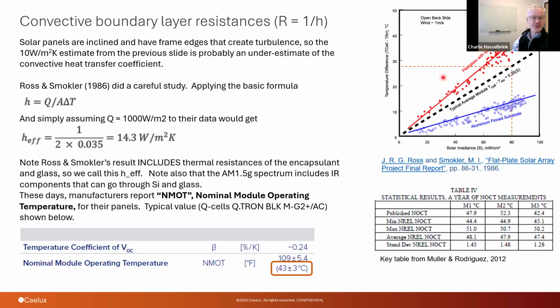We can go through the math in some of the papers, but I just provided these as reference for what those convective heat transfer resistances look like. It's something, and then 1 over this heat transfer coefficient is the resistance. So you can go through this analogy, draw the data from the literature. This is obviously a very old study. This has been well understood for a long time. Not surprising that the temperatures that you get between the cell and the air are linearly proportional to the irradiance that you have on the device. And from that, you can derive these coefficients that you need in order to do the analysis.